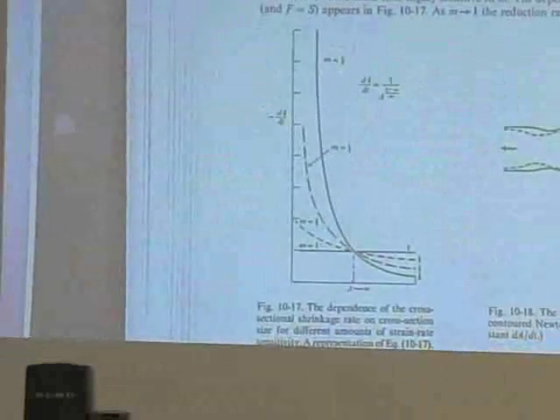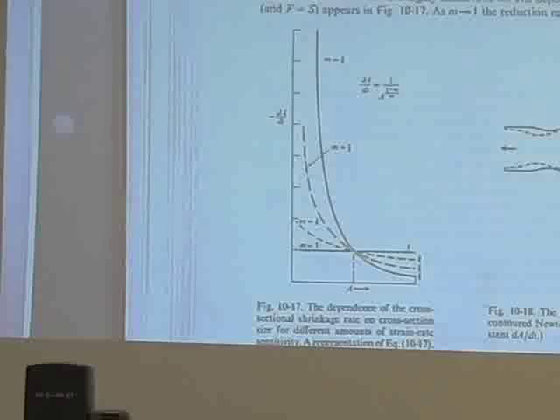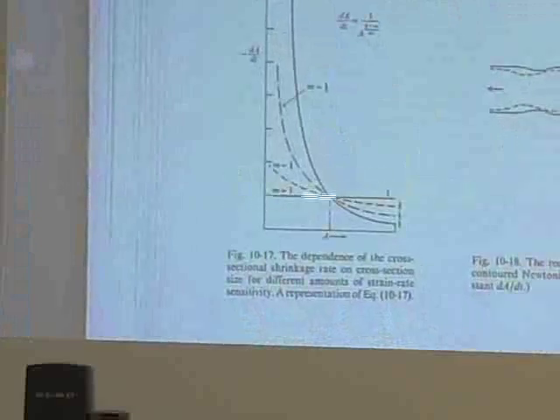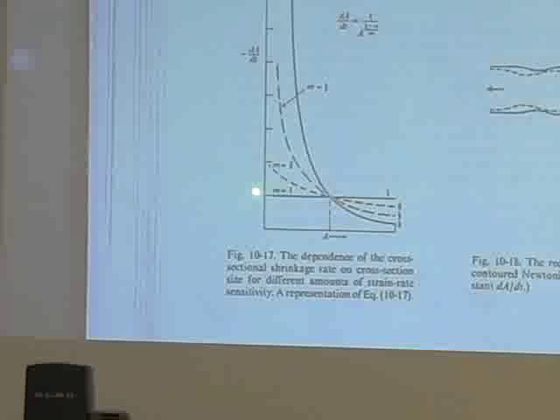If you go to think about superplasticity in necking and start looking at the strain rate in terms of these dA, dA/dt, so it's a strain rate as a function of time, you can write down formulas, and it turns out that for a pure Newtonian liquid with m equal to 1 has no strain rate dependence in terms of the rate at which you're pulling it. So it doesn't matter whether you're pulling it fast or slow, it will neck down the same.